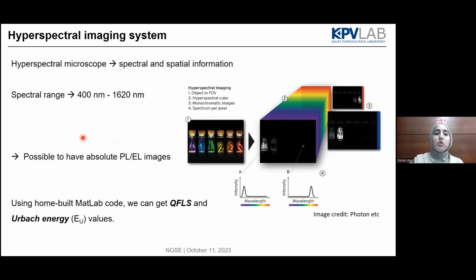And we can do it in the absolute mode. That means that you can get the absolute photoluminescence emission and also the electroluminescence emission. And having this data cube at the end that you can see here, we have a home-built MATLAB code, and we can get the quasi-Fermi level splitting or the Urbach energy or the PL peak position shifts, for instance, after the light illumination. I mean, continuous light illumination.